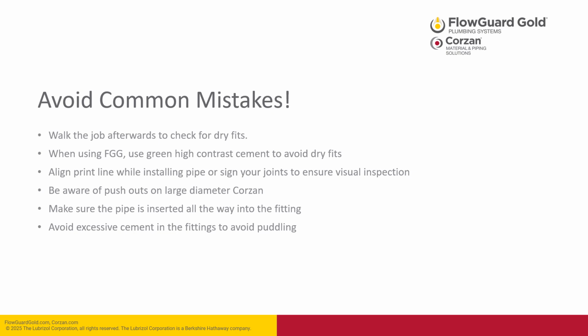There are a few common mistakes that are easy to avoid. Walk the job afterwards to check for dry fits. And if you're using FlowGuard Gold, use the green high contrast cement to help visually identify joints that may have been missed. Try to align the print line while installing your pipe, or you can sign joints to ensure visual inspection by the installer. Be aware of push-out on large diameter Corzan.